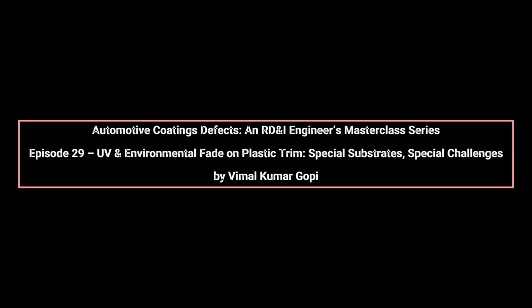Additives are critical to controlling fade. HALS, hindered amine light stabilizers, interrupt radical chain reactions caused by UV, while UV absorbers convert high-energy photons into harmless heat. Surface waxes and slip additives reduce micro-roughness formation and maintain hydrophobicity. However, all these additives are consumed over time. Migration to the surface initially protects the top layer, but repeated environmental exposure, rain, abrasion, temperature cycles, depletes these additives, exposing the underlying polymer to degradation.